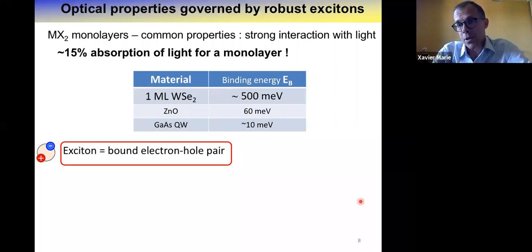But one very important element we have to consider is the fact that the electron and hole in this monolayer are strongly bound, forming a very robust exciton. And this very robust exciton, in addition to the direct gap, explains the very large absorption you get for monolayer. It's really amazing compared to other semiconductors that a monolayer less than 1 nanometer thick can absorb up to 15%, 20% of light. It's really spectacular. And this comes from the fact that you have excitons with a giant binding energy of the order of a few hundreds of millielectron volt, depending on the environment. We will come back to this point.